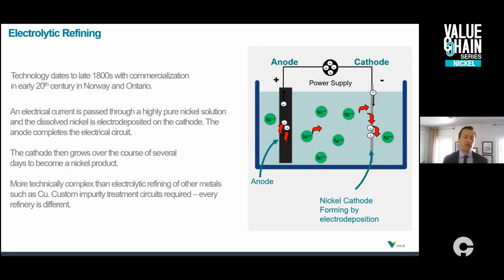You have an anode, which is basically a sheet of impure nickel metal, like a nickel intermediate that's been cast into a slab of material. And then on the right-hand side, you have a sheet of pure nickel. And as you pass an electrical current through the anode and the cathode and the plating bath, nickel dissolves from the anode and plates at the cathode. And after 5 or 7 days, you end up with an acceptably thick sheet of very pure nickel metal.